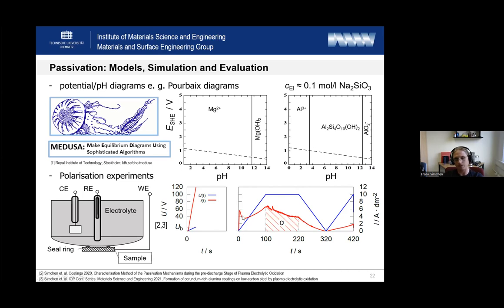Then the formation of the passive layer takes place. The electrical resistance is increasing, so we have a lower current flow. And then step by step, the current is rising over the measurement time. And we integrate the flowing charge, the flowing current, over a certain time of this experiment, and get such a characteristic sigma value. And this helps us for the determination of comparable characteristic values.